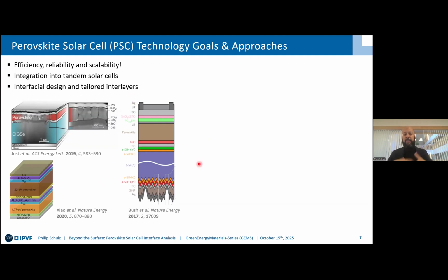As you see, there's a multitude of different interlayers and interfaces, and what is the best choice, for instance, here for the hole transport layer: nickel oxide, always nickel oxide, something else, self-assembled monolayers maybe? What are the requirements for the top contact, and how can you actually make a conformal top contact that helps to promote charge extraction from the perovskite, but at the same time also acts as a pre-encapsulation layer that increases your stability?